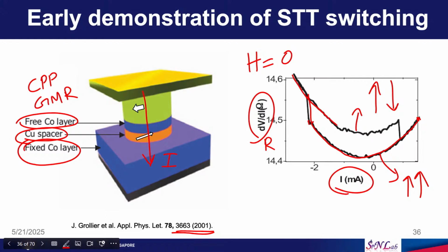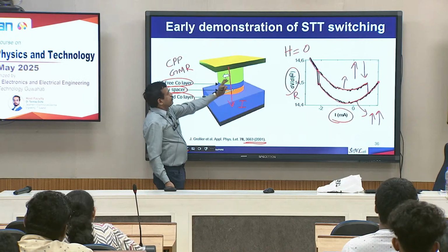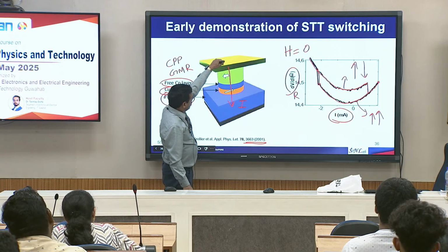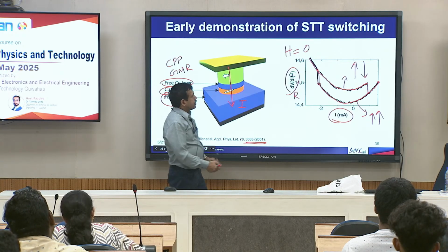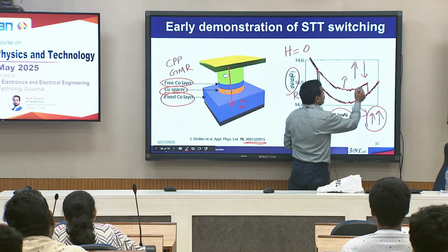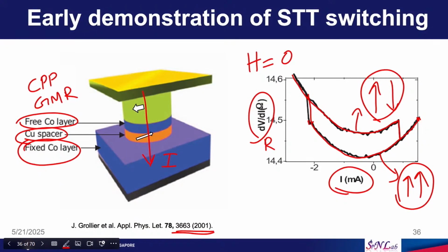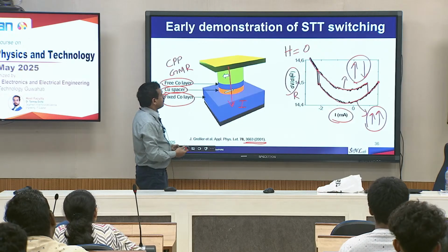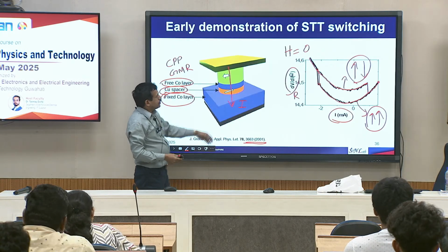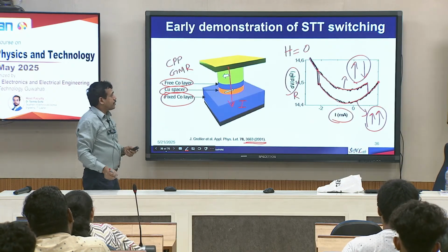Now, you go along this line, change the current direction. So, now negative to positive, at certain value you see that it has switched from anti-parallel to parallel configuration. Okay. So, here they did not apply any magnetic field, only by changing the current amplitude and the current direction they can go from parallel state to anti-parallel state. So, this experiment proved that we can switch the magnetization states by sending current through the device and by using spin transfer torque mechanism.